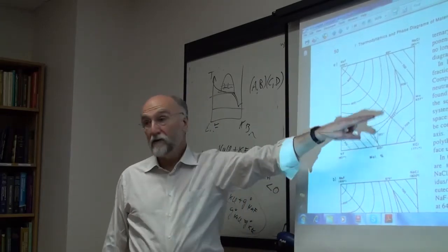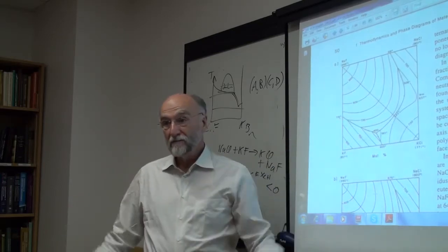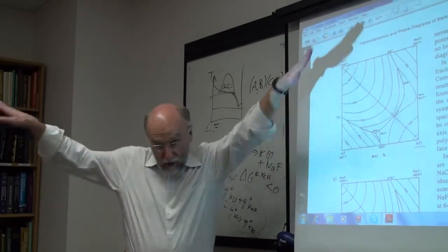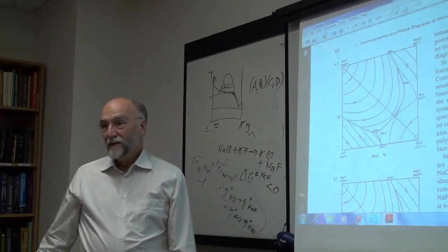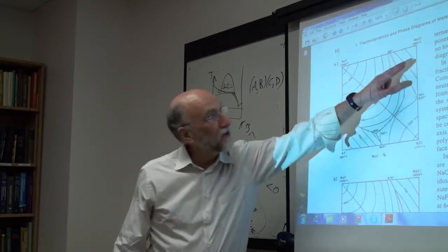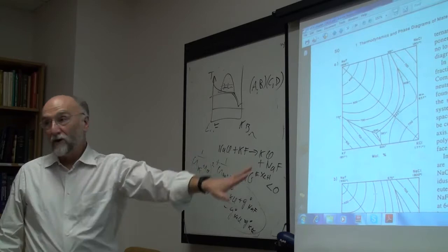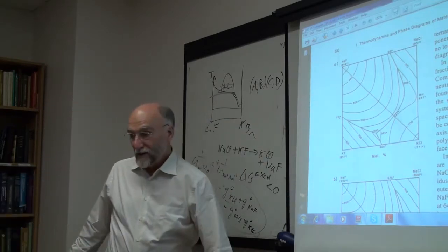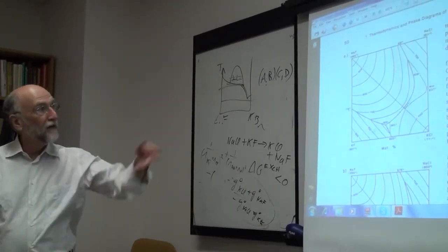There'd be no positive deviation along here. You just get NaF and KCl mixing more or less ideally, which means the liquidus would be way, way lower, hundreds of degrees lower. It just wouldn't work. So you might fit your binaries nicely, assuming a molecular model, which would be very simple, but it's not going to work in the reciprocal system because you have two sublattices, and if you don't take the two sublattices into account, then the whole thing completely screws up by huge amounts.